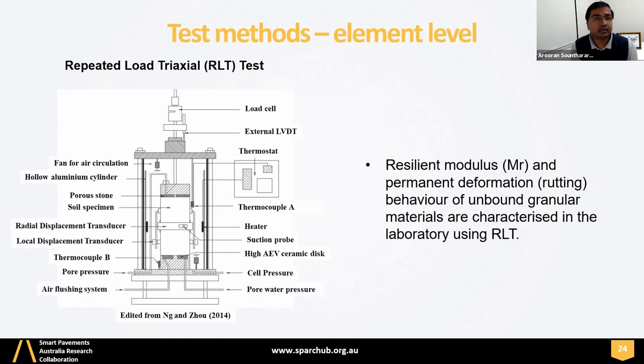How do we test the performance of these materials and identify the necessary engineering properties to design them? Right? So UGMs, different types of unbound granular materials, like I said, class 1 to class 4, are normally analyzed or examined through resilient modulus, right? Which is a property used in the pavement design as an input parameter, and the permanent deformation, which is rutting, right? Rutting occurs under cyclic loading, as I mentioned. So typically, these two parameters are examined in the laboratory using RLT, the repeated load triaxial test.